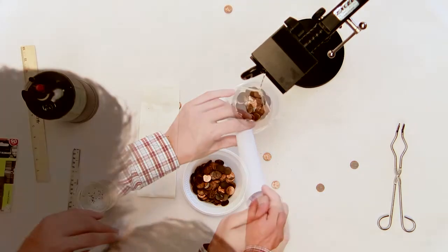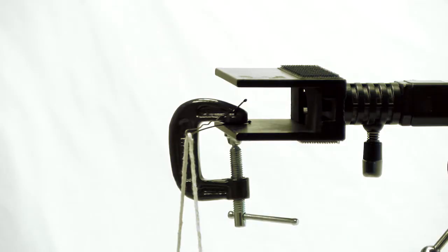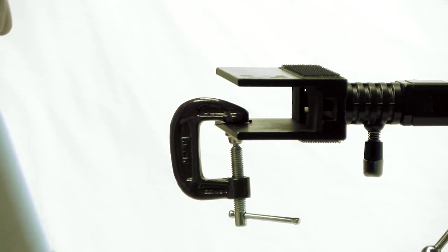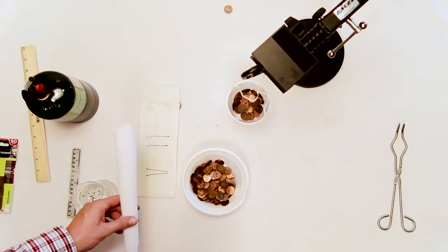If properly quenched, this bobby pin will break before reaching the maximum load of 300 pennies, usually at a loading of 70 pennies.